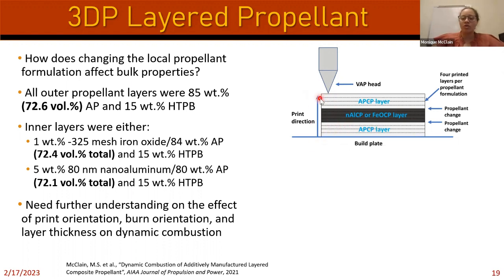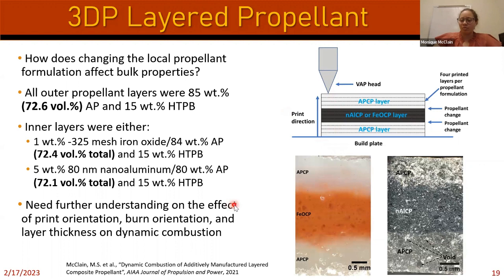So the outer layers are just normal ammonium perchlorate propellants, and the inner layer either has a bit of nano aluminum or a bit of iron oxide. So it should burn faster than the outer layers. And we have some images of what those look like. For example, the white is essentially the ammonium perchlorate propellant, so no additives there. And then the middle layer has a bit of iron oxide in it, which is why it's red. When we printed these, they are about 1 millimeter thick layers.